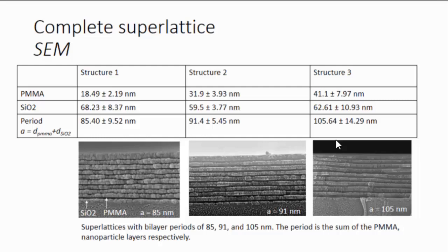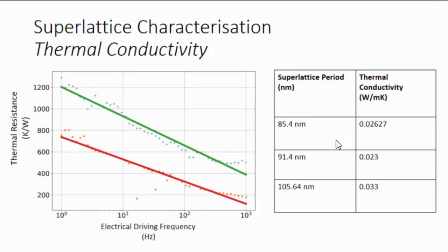So this is an example of the kind of data you get out of an AC resistance thermometry experiment. Over here, you can see this top green line represents a frequency sweep, a full thermal transfer function sweep of the superlattice sample. And then below, you can see the control, the substrate only sweep, which all this means is that the distance between these 2 lines implies the thermal conduction of the superlattice alone. So we measured a value between 0.023 watts per meter Kelvin at the low end and 0.033 at the high end. This is all done at room temperature and atmospheric pressure.